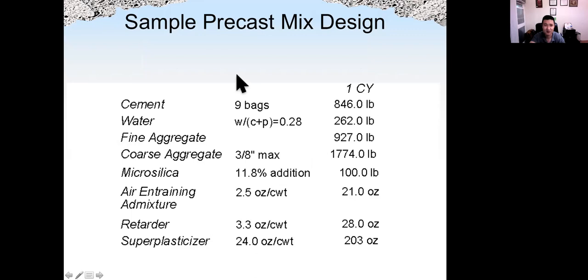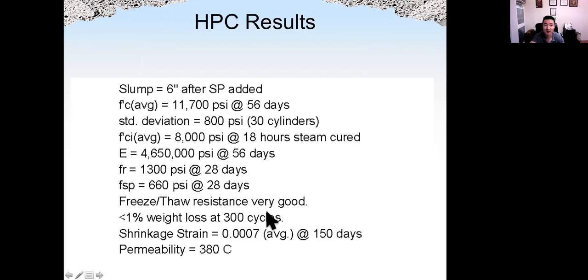This is another sample mix design for precast concrete. And that's the result for high performance concrete: 11.7 KSI at 2 months. Very durable concrete, very good freeze-thaw resistance. Shrinkage acceptable and very, very low permeability.